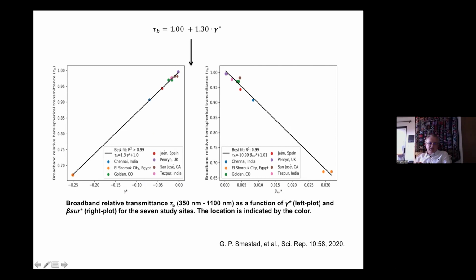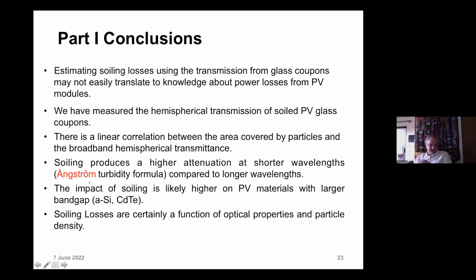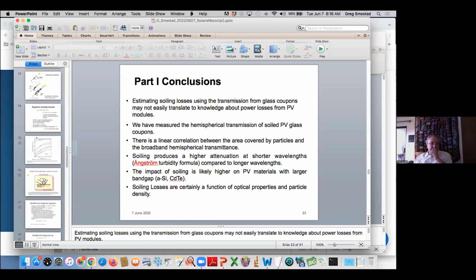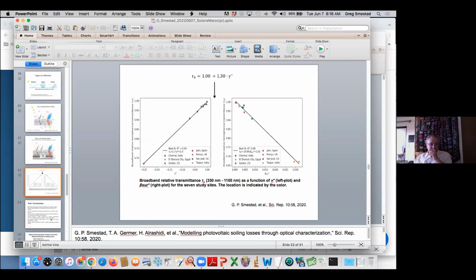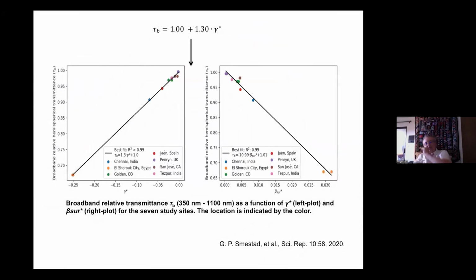And so we did this for Golden, Colorado, for Egypt, for Chennai, for Spain, for England, for San Jose, for Penryn, England, and Tezpur, India. And so we looked at the values that we get for those different Angstrom plots where we fit to the data. So these are fits to the data. And we looked then at the value of gamma that fits the data best. Plotted its point. Again, the broadband relative hemispherical transmittance is a lumped transmission, not the transmission.